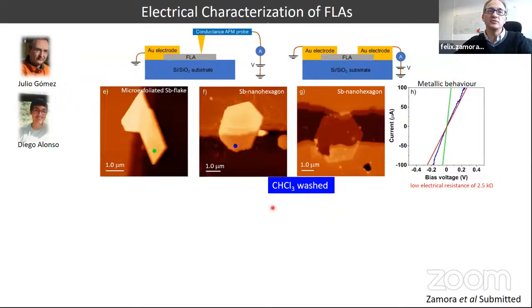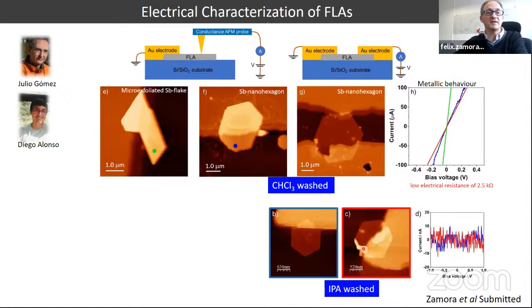Okay, and then we decided to use these hexagons, the ones washed with chloroform, to establish electrical contact. And here I showed you the two experiments that we did in collaboration with Julio Gomez and Diego Alonso. Under this configuration and this configuration, we observe metallic behavior for our hexagons. But this dramatically contrasts with when we use samples washed with isopropanol: we were unable to detect any current flowing when we contacted. This is the gold electrode, and then we use the conductive AFM tip, and we were trying to apply a kind of pressure on our hexagons, and nothing happened.